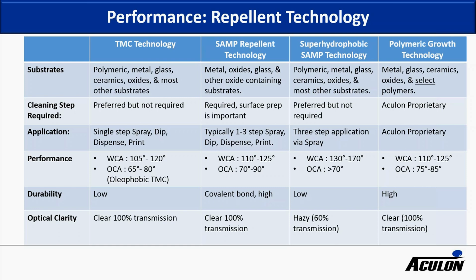SAMPs, on the other hand, really require an oxide, so they're mainly used for metals, semiconductors, glass, or other oxide-containing substrates. Here the bonding is especially important, so you need to make sure that you get the surface clean. There's usually a couple of steps where you have to clean, coat, and then in some cases you may need to do some rinsing. The performance level is very high in terms of repellency. We get water contact angles between 110 and 125, and industry-leading oil contact angles, this is hexadecane, between 70 and 90 degrees. Very good durability. They're covalently bound to the surface, and because they're so thin, there's optical clarity.